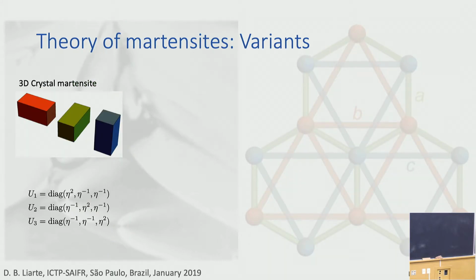So there are 3 ingredients from the theory of Martensites that I'm going to use to describe this Smectic microstructure. One of them is the variants. And I'm showing here the 3 crystal martensite variants, which correspond to deformations along the 3 Cartesian directions. And you can, for instance, describe these deformations by distortion tensors. You don't have to be worried about these formulas. But each distortion tensor here is associated to one of these deformations.